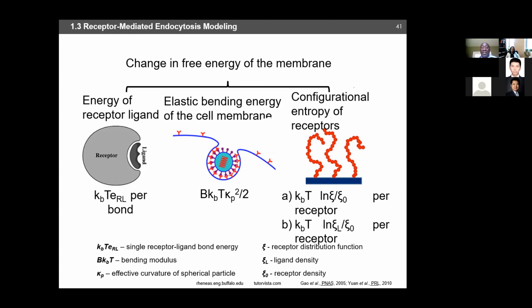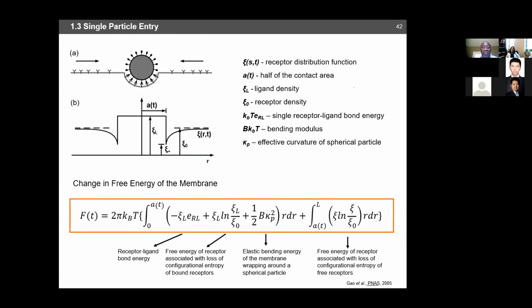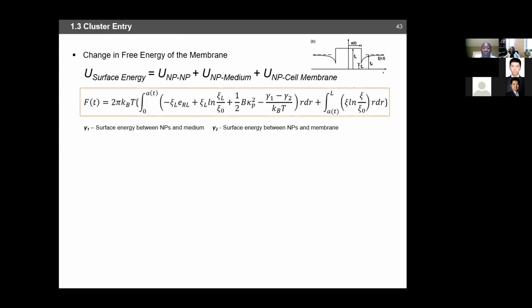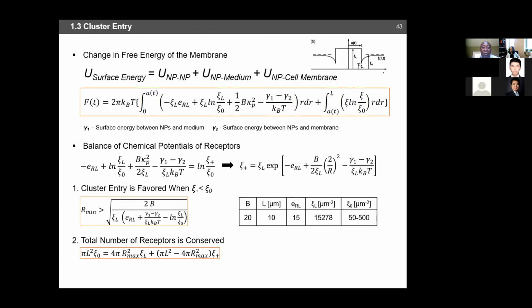And so if one thinks about each of these energy components, then you can add the contributions from each of these to get the overall energy, the free energy change, for the entry of one particle into the membrane. And this is shown here. Well, one can also do the same for a cluster. In that case, you have to think about the free energy change of the nanoparticle interaction, nanoparticle medium interaction, and nanoparticle cell membrane interaction. And if one adds all of this together, you can get the total energy change for the entry of a cluster.